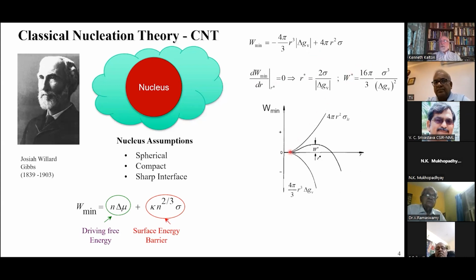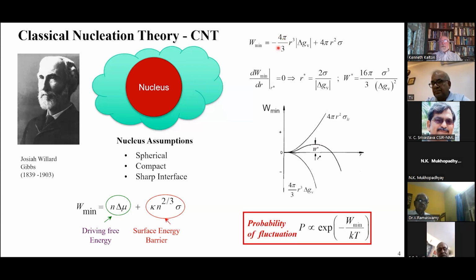If we look at the amount of work required as a function of cluster size, it first increases due to the surface energy penalty, and then it begins to decrease due to the larger contribution from the volume free energy. Gibbs said that this was the relevant quantity, and if you want the probability of having a fluctuation leading to nucleation, you just take a Boltzmann-like factor of the work of cluster formation normalized to kT. That's the thermodynamic model of nucleation that we still use.